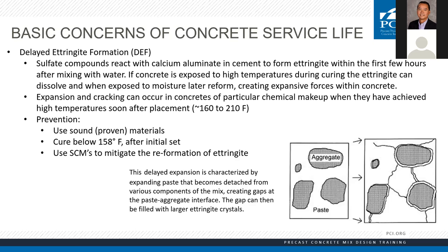What is DEF? As cement particles hydrate when blended with water, they transform from the four basic compounds — tricalcium silicate, dicalcium silicate, and so on — into calcium silicate hydrate. In that process, a mineral called ettringite comes into existence. In a perfect world, all ettringite would form and then be consumed in that process and no longer be present in the hardened concrete. But because of different curing methods or lack of curing, some ettringite can either remain during hydration or form in a delayed state. When water later combines with that ettringite, it creates an expansive gel that puts force on the concrete from inside and creates cracking.